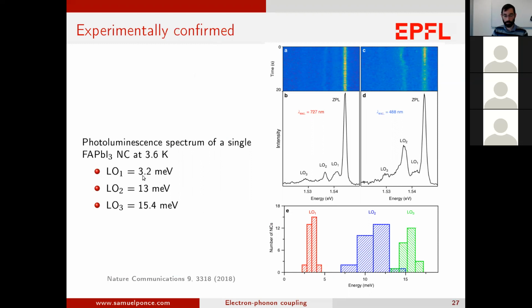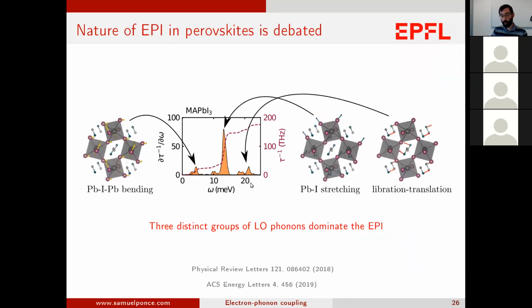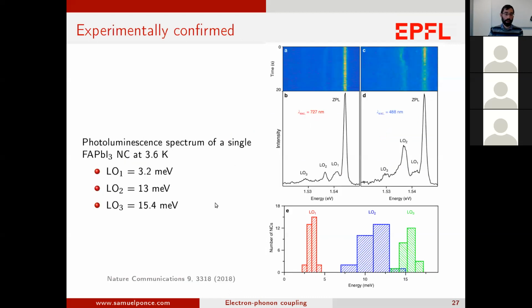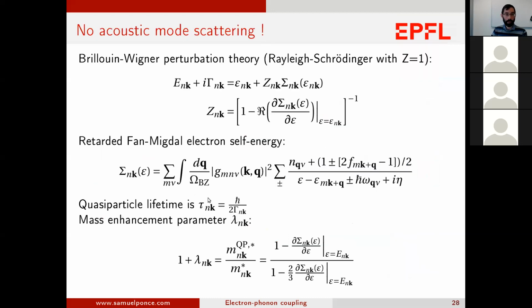So one at 3 meV, one at 13. Those two are the same. And then the third one is at 15 in this case. And in our case, it's more like 20. But this is because the organic molecule is different. In this case, it's MA, and in the other is FA. So it makes sense that this third mode is a bit different. And so I think that was very nice to verify.